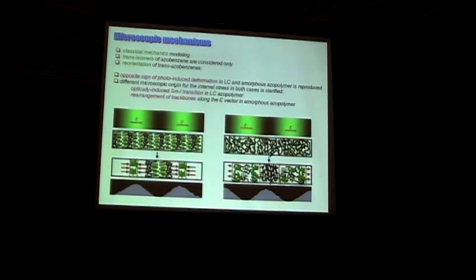To conclude, I will present here the slide. So what we did here is classical mechanical model. We consider only trans-isomers of azobenzenes, and the only effect of the light was reorientation of trans-azobenzenes. And of course, this is very coarse modeling.